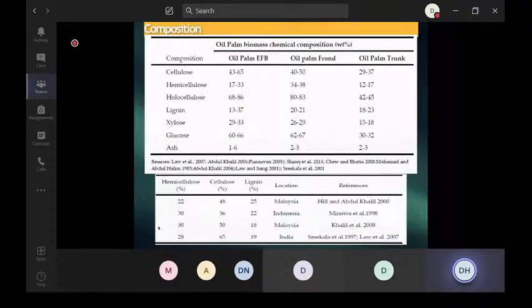When you are talking about bio-waste material, you are very sure about their composition. You can see the oil palm EFB, that is the fibers, and then oil palm frond and oil palm trunk. Although they are from the same category, the cellulose content varies a lot. Oil palm frond is 40 to 50%, oil palm fibers 43 to 65, whereas oil palm trunk is much less, 29 to 37. And again hemicellulose, holocellulose, lignin, xylose, ash.